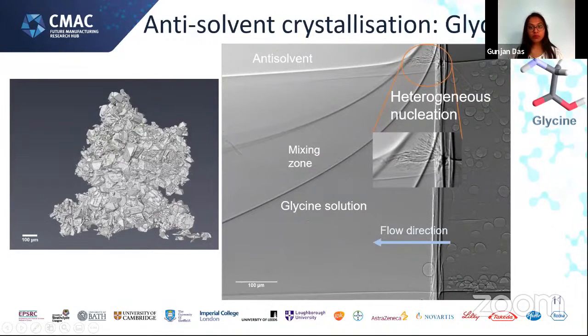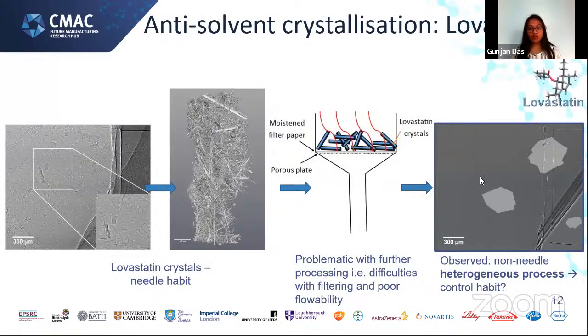What we have also done was we have collected the resulting slurry of glycine solution, and we have performed a quick tomography to see the microstructure and the crystal habit of glycine crystals. We have also done antisolvent crystallization studies of lovastatin. As we know, lovastatin always crystallizes as needles, and we were able to observe a lot of heterogeneous processes taking place on the outer walls of the tubing.